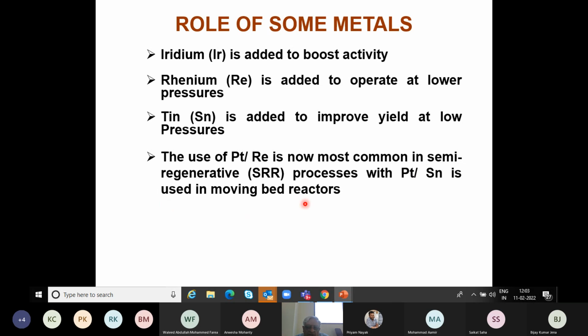Or at least what we call continuous catalyst regenerator. So there are two types of technologies people use. In fact, in India we have both these technologies operating: semi-regenerative reformers as well as CCR. In semi-regenerative reformers, you use platinum rhenium, 0.3% platinum, 0.3% rhenium. And in CCR reformers, we use 0.3% platinum and 0.3% tin.